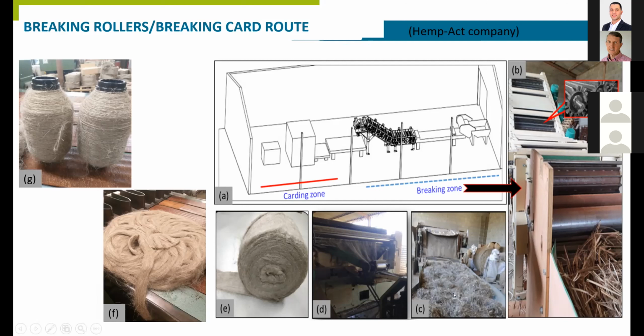And this is why those fibers need to be introduced in a card. So breaking card, which has two main important roles. The first one is to homogenize the fiber length and to try to align the fibers as well. At the end of the day, after the breaking card, some big slivers, like here in part E, can be obtained. And those slivers can be drawn with a machine we saw previously, doubled, homogenized to obtain some slivers like that. And at the end of the day, roving type yarns as well as for the scutching hackling approach.